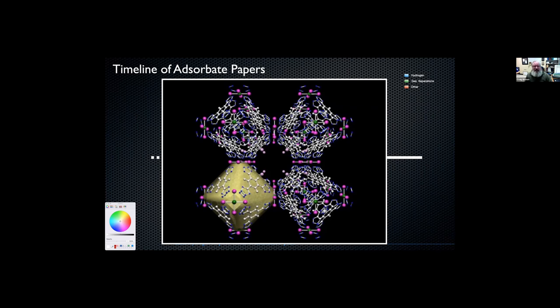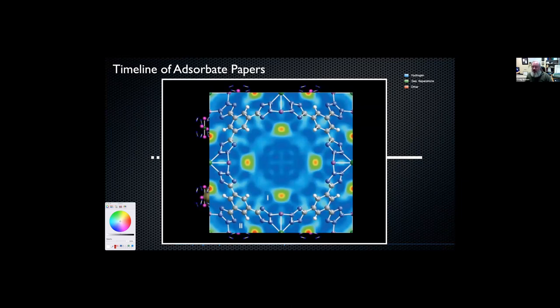This is a copper benzene tetrazole system. You can see that there's a central benzene ring surrounded by 120 degree tetrazole rings that bind to these metal ions with a central chloride ion. And these are partially solvated, but you can easily find D2 molecules adsorbed in those systems. And they look like a blob because they're quantum mechanically averaged. I'll show some INS data later that shows that they're quantum molecules. And so you shouldn't expect to see them as individual hydrogen atoms. You should expect to see them as some kind of mass of scattering density.